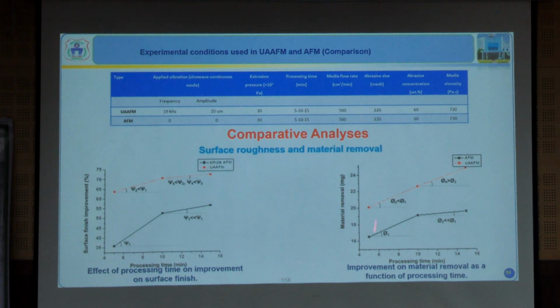So the second result shows the material removal in milligrams. We are not calculating any rate. We wanted to see, before and after, how much material is removed. We observe here the black color shows simple AFM, whereas the red color shows UAFM. One important observation here.